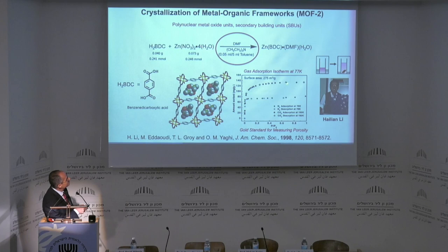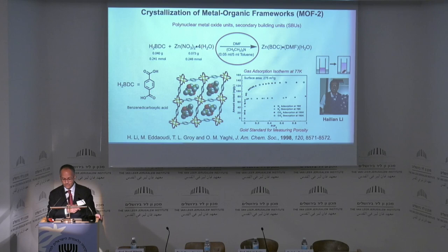And it was very exciting to me, because although the surface area was kind of low, it allowed us to determine the porosity, as in the surface area and pore volume, and compare the porosity of MOFs with the more established porous materials like zeolite, mesoporous silica and porous carbon for the first time. And so I was excited to see that these are architecturally robust and that our secondary building block approach, our cluster building block approach, can produce architecturally stable results. And so this was the first proof of porosity for MOFs, and we published it in